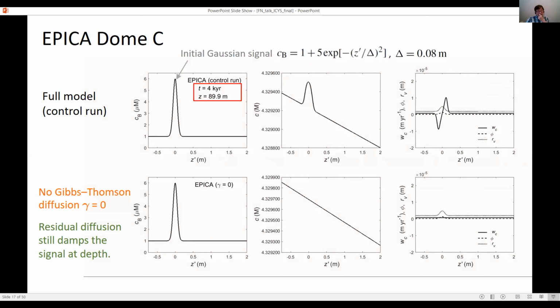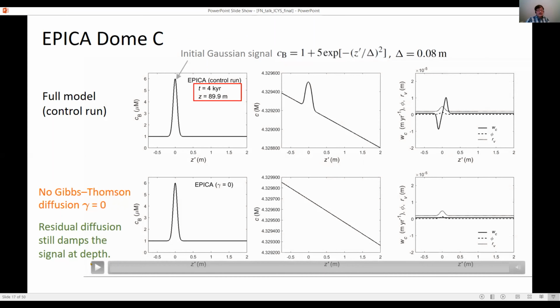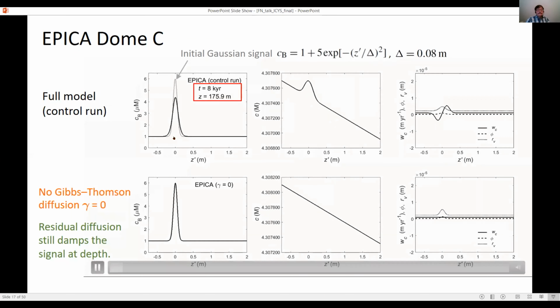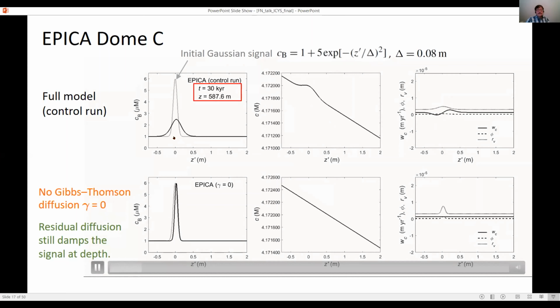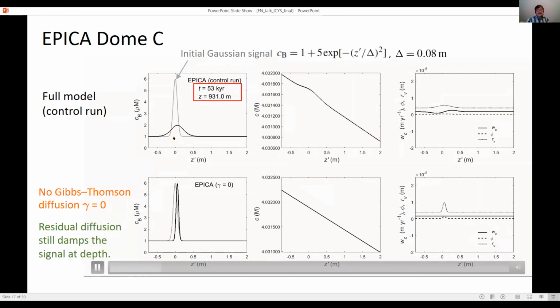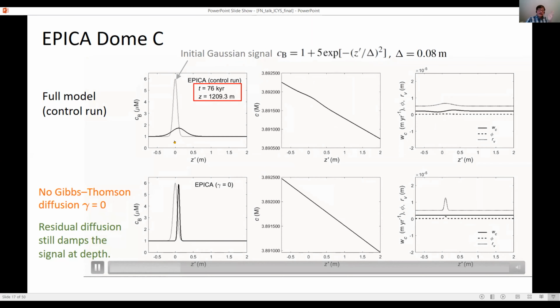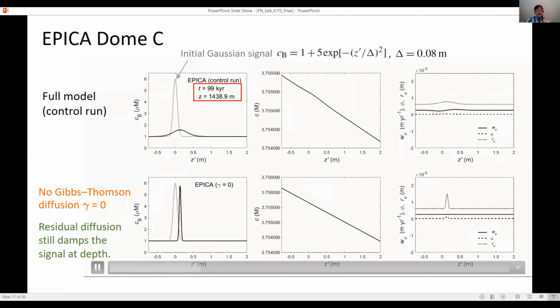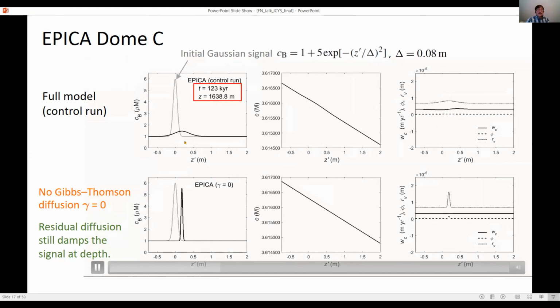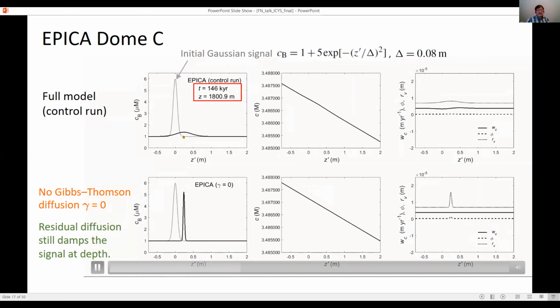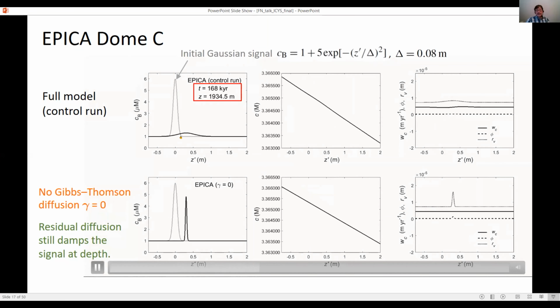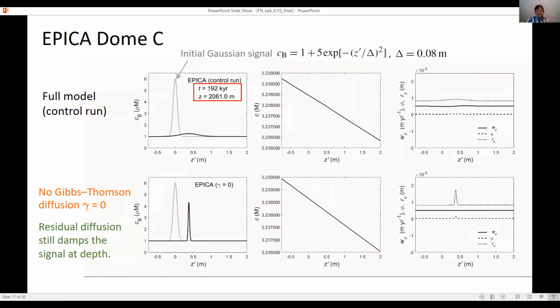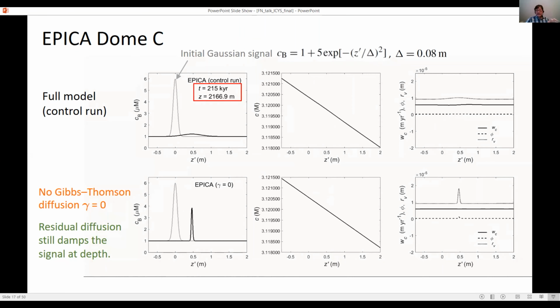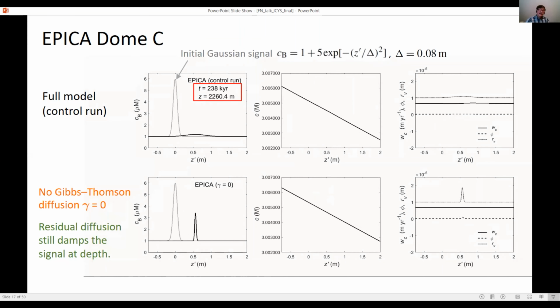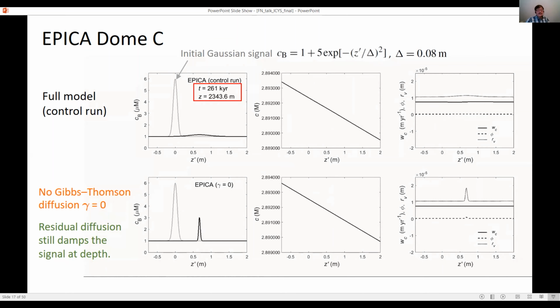Here is an equivalent experiment of Dome C, same injection really. Again, two experiments. Rapid decay of signal amplitude again. At Dome C, there's a bit more of the temperature gradient, even in shallow ice, so we see more visibly the migration. We're about halfway down now, and most of the signal content is again gone. And remember, I'm just modeling the vein impurity contributions, not the impurities in grain boundaries or the lattice.